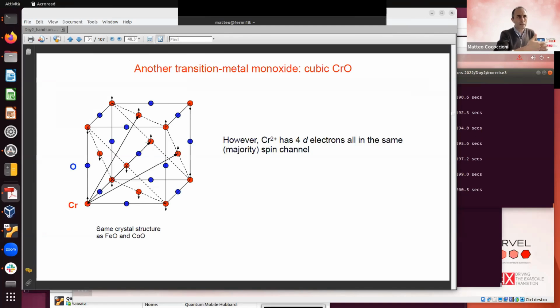Now, if you relax these materials, they tend to deform, to get away from the cubic symmetry, and these fractions are no longer exactly equal to 1/2 or 1. Typically they elongate or compress along the 1, 1, 1 diagonal, which is the one joining this chromium with this chromium here. These coordinates change a little depending on the amount of deformation the system wants to go through.